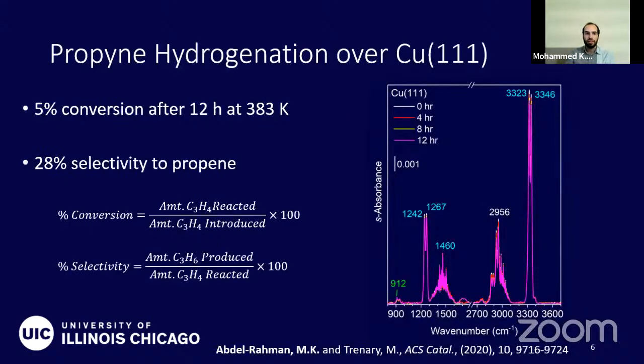And so first we start by looking at the hydrogenation over a bare copper surface. So we used the copper 111 surface. And after 12 hours at 383 Kelvin, we found that only 5% of the propyne reacted. And so we can see that here by all these spectra looking almost the same, very small intensity change here in 3323, and very small growth of 912 wavenumber. And so the selectivity and conversion were calculated based on these equations, where conversion is the amount reacted versus the amount introduced, and selectivity is the amount of the desired product formed divided by the amount of the starting material.